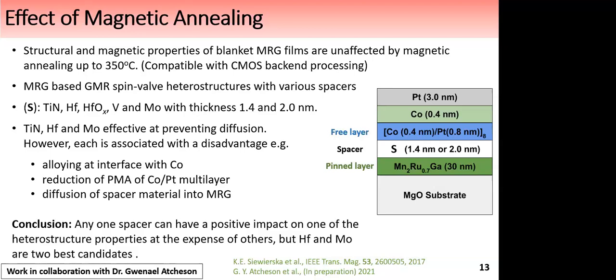So in conclusion, any one spacer was found to have a positive impact, but also it could have a negative impact at the same time on other properties. However, hafnium and molybdenum presented a compromise and are the best candidates for spacers reducing diffusion.